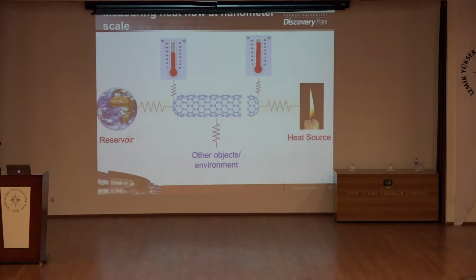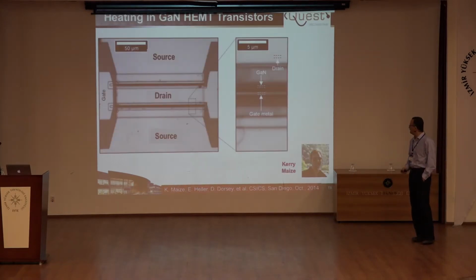We can mimic that, and that's what a few very nice experimental works do. They put this in a suspended platform, and they take a lot of care, typically PhD students, 6 months of work, to make sure that the heat only comes here, and you measure temperature precisely. You define a thermal conductivity. But from a practical point of view, that's never useful because, whenever I have any electronic device, what I have is a heat source, and I have the heat sink, which is the lab. And the thermal resistances are not negligible. So boundary conditions matter in real devices.